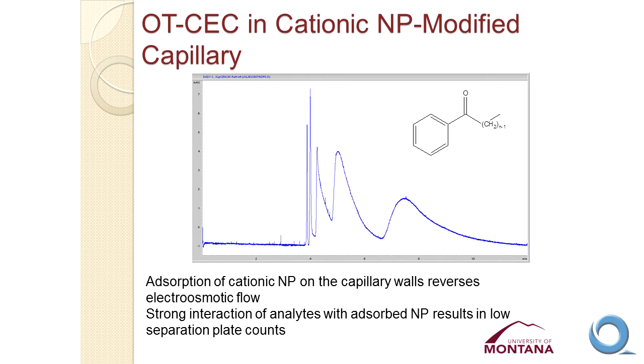And what we realized, after first considering that maybe the cationic nanoparticles just were not going to work, was that what's causing these big broad peaks and this retention is actually interaction of these hydrophobic analytes with the nanoparticles that are adsorbed on the capillary walls. It's not something we wanted to have happen, but it is what's happening. And so that causes this retention.